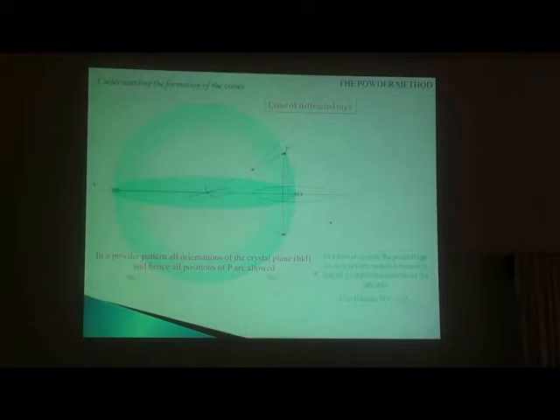For Bragg's law to be satisfied, the point should be on the surface of the sphere. Then only the geometry will be satisfied. So this sphere intersects with the reflection sphere, giving you a circular section, and the diffracted beam comes out through the periphery of this circle. So in effect, what you get is a cone like this. The intersection will be a cone like this. So the diffracted beam emerges from the crystal as cones.